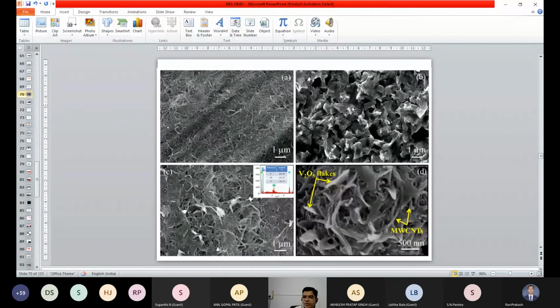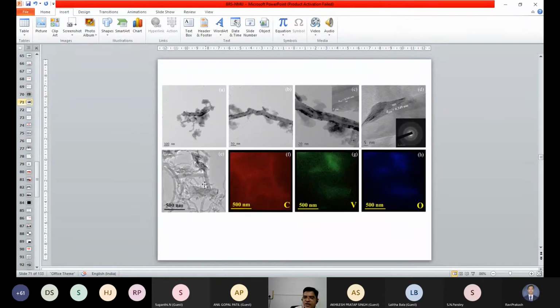So this is the surface morphology of the vanadium oxide when you are coating on the stainless steel, and when you are coating on the carbon nanotube, you can see the flakes of the vanadium oxide coated on the carbon nanotube. These are the flakes which are pseudocapacitive coating on the EDLC type of carbon nanotube having very high surface area. This is again the EDX mapping we have performed to see vanadium and oxygen inside this one